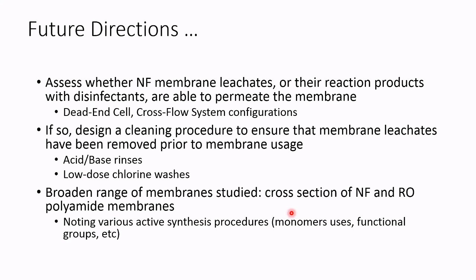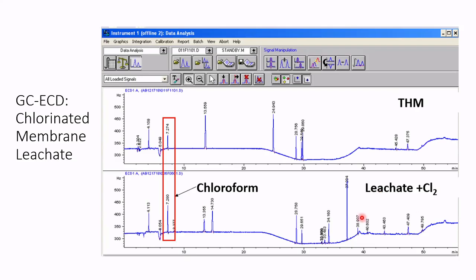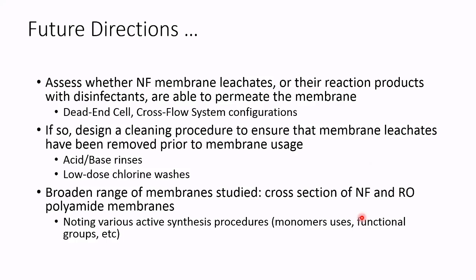So future directions, we can assess whether nanofiltration membrane leachates or their reaction products with disinfectants, so the MPD that was coming off, or some of these chloroform and low molecular weight compounds that we see here. The next step would be, are they able to permeate, right? Because right now our tests are in these static systems, and I'm not actually pushing the water through the membrane. So are these leachates and byproducts able to permeate the membranes? And recently studies have shown that yes, they're able to permeate through the membrane and be in the clean water side, which is critical.